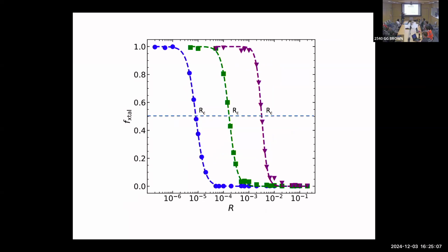Based on what I just said, you can calculate the fraction crystal. Every atom is determined to be crystal-like or non-crystal-like. Then you count up how many are crystal-like and divide by the total number of atoms, and you get a fraction which goes from 0 to 1. You measure this as a function of different cooling rates in different systems. Here's one system, it could be nickel, and here's another one, it could be aluminum.